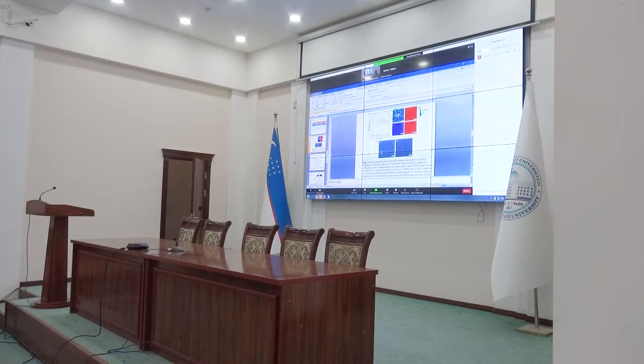Okay, figure 5a shows the XRD pattern of the films L1 and L2, and you can see the quality of samples grown on this type of substrate is the best. Only bismuth telluride with direction 006 is shown, and a very small peak from the gallium arsenide substrate, but no other crystal direction was observed. While in film L2, which was grown directly without miscut, you can see there are some crystal domains with different additional crystalline directions. This is clearly seen in figure 5b.